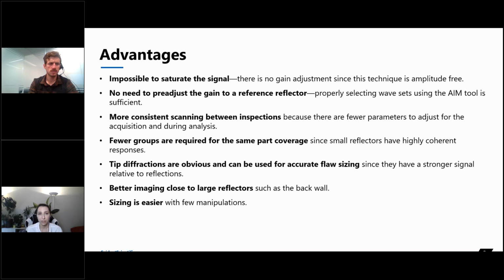There's fewer groups that are often needed for the same inspection. So for example, if we have something with an amplitude-based technique, so with PAUT or TFM with TT, let's say that we have TT and we have a reflector high in the upper corner of our zone of interest. Sound might not go there, so we would use another group, or 4T, for example. But because here we're not really looking at the sound response or the amplitude response, as long as there's sound going there, we'll see the diffraction, we'll see the change in the phase. So often we've noticed that we need fewer groups to perform the same coverage.